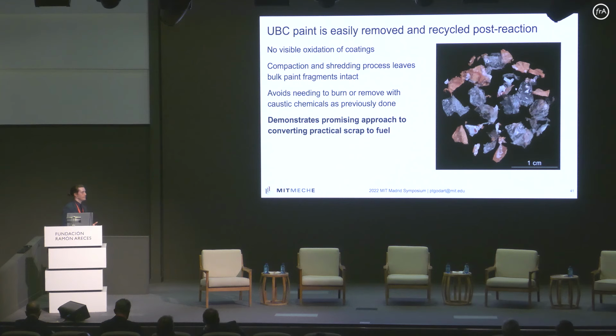In this process, the paint on the outside of the used beverage cans can be easily removed. It's not oxidized or damaged during the reaction process. What's interesting here is that these used beverage cans actually have a polymer coating on the outside and the inside, and essentially what we're doing is reacting the aluminum from in between those polymer coatings. And you can actually read the labels off these paint shreds that come out of our process.